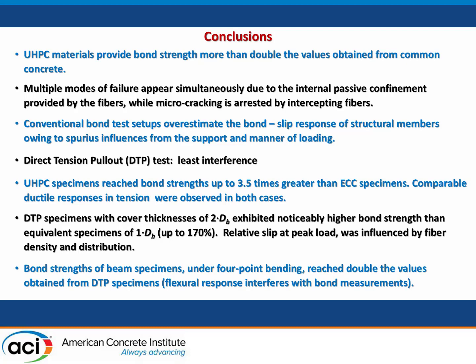The direct tension pullout specimens with cover thickness of 2 Db exhibited noticeably higher bond strengths than the equivalent specimens with 1 Db. And the slip amount corresponding to peak strength really depended, from what we saw afterwards by cutting the specimen, on the fiber distribution and the fiber density.